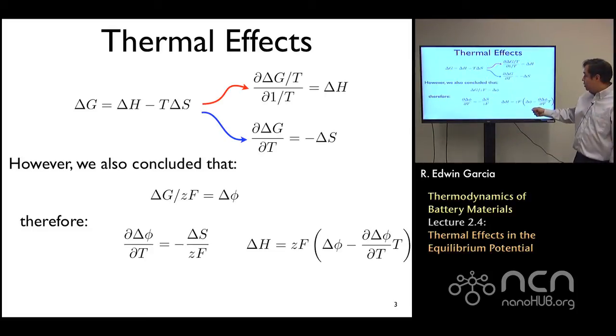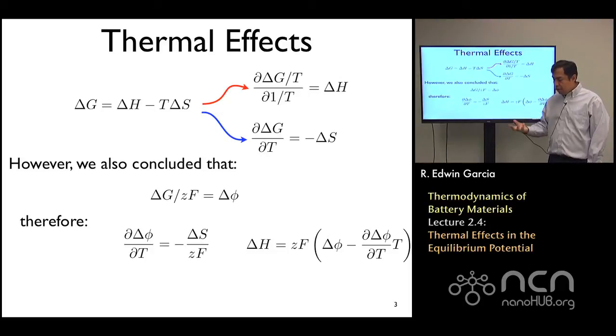Then I just solve for ΔH, and I will find that by simply measuring the voltage and the voltage dependence with temperature, I will have a measure effectively of the enthalpy, basically having a very simple graphical way to measure the enthalpy of an electrochemical system.